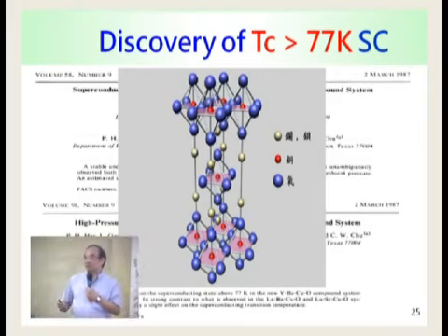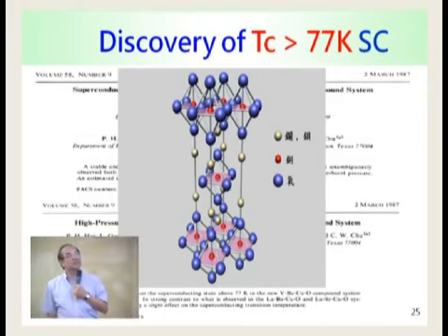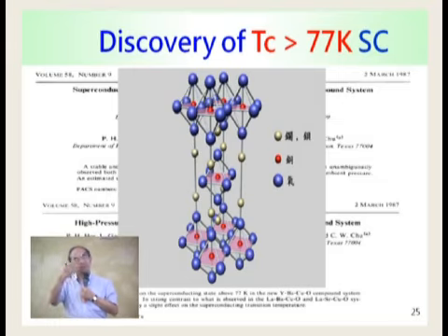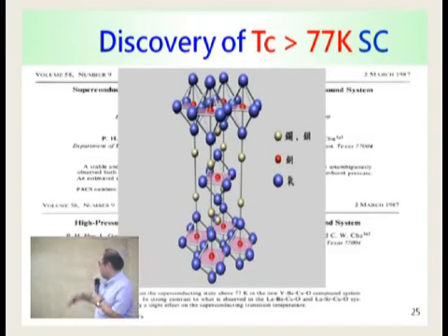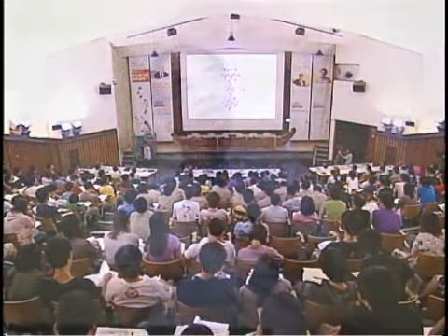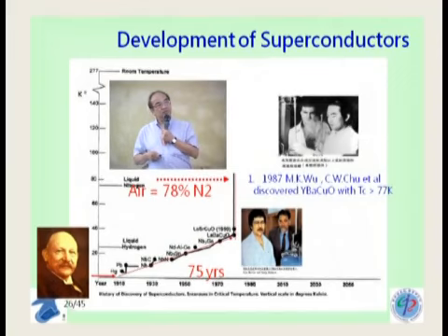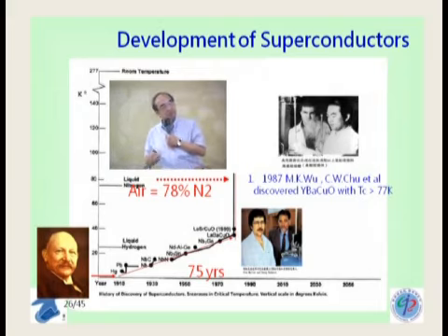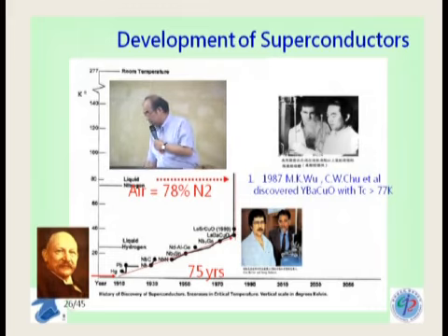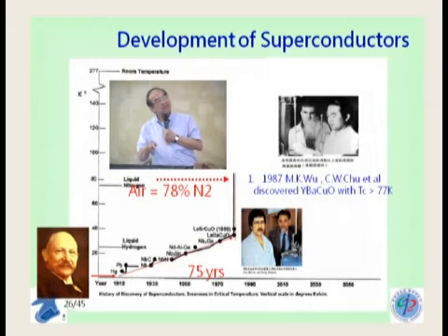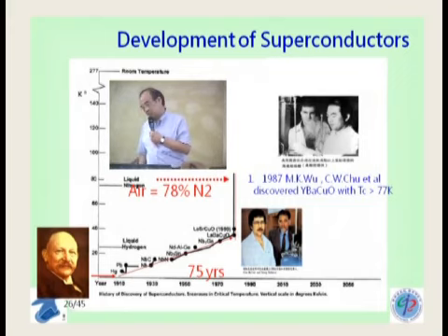Okay, so that's how the follow-up of Dr. Bednorz's work got to this high TC. And we know later, very soon, about 2 months later, the structure was identified, that this is basically still a perovskite in general, but there's some layer, the pyramid and some layer structure inside, okay? And so that was 87, and we went to Houston and Alabama, and the Houston group then got the YBCO work out. Okay. Well, that was a long time ago.